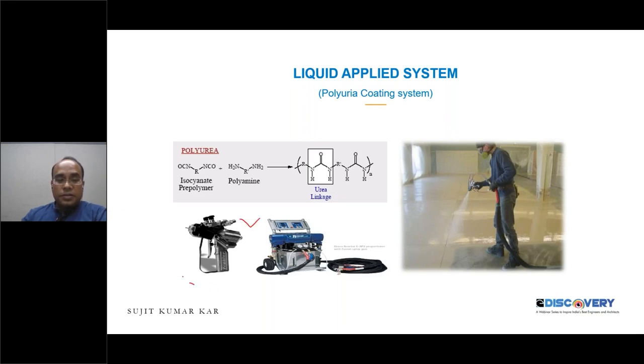This is a spray gun, and this polyurea coating is very precious. It is a two component system, and it is heated up to 85 degrees Celsius before mixing, and it mixes in the nozzles. Once component A and component B mix, it sets immediately. So it is a very good latest technology you can use, and it has good UV resistance properties.